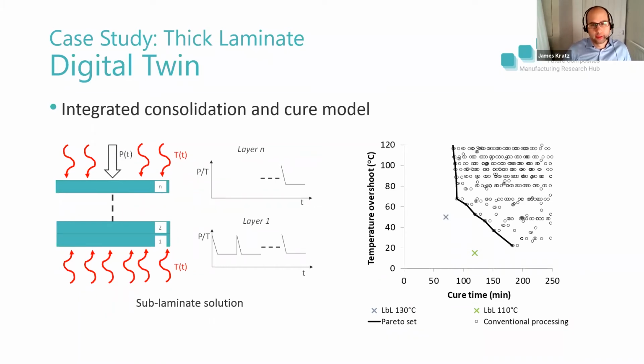And if we run our digital twin, where we've coupled the consolidation and the curing together, we can see that it's always going to be more effective for thick laminates to approach this problem with a sublaminate type solution. If we look on the right-hand side, we can see cure time as a function of temperature overshoot. This is for a target cure of 120 degrees centigrade. Within our conventional process, we can run a series of solutions, and the minimum tends to become the Pareto front. By examining the layer by layer process run at a couple of different boundary conditions, the gray X will show you how, if we wanted to process the component in an hour, we could do that, but we'd have a 50 degree centigrade overshoot.